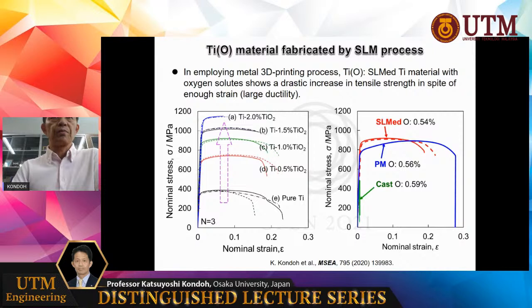Compared to other materials like powder metallurgy process materials and casting process materials at almost the same level of oxygen content, about 0.5 to 0.6%, SLM materials show a higher yield strength compared to powder metallurgy materials. This is due to the hardness of martensite, but they showed a little decrease in elongation, or strain ductility, but close to 20%, which is enough for structural materials.